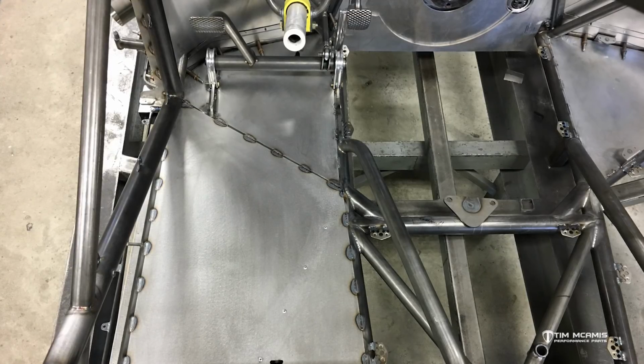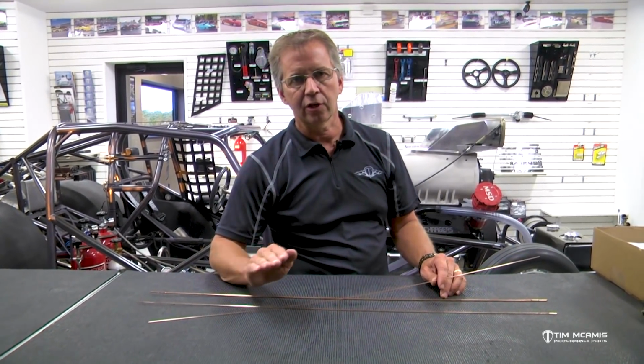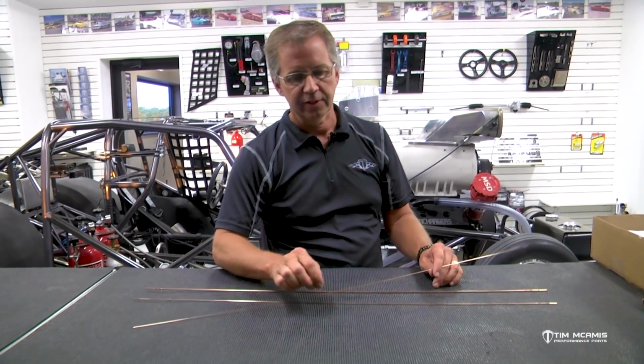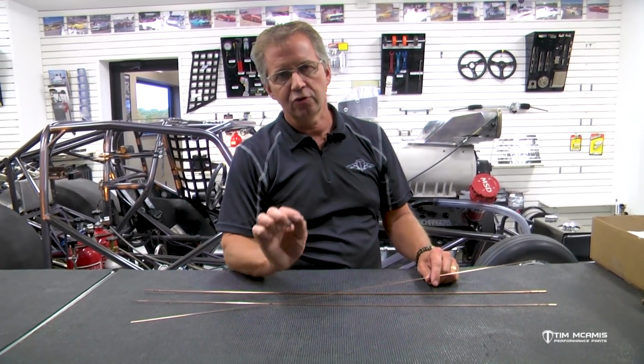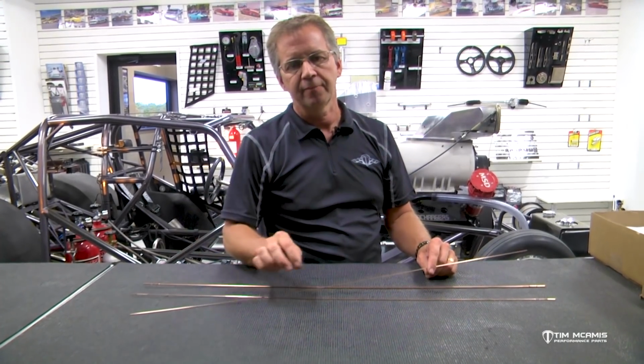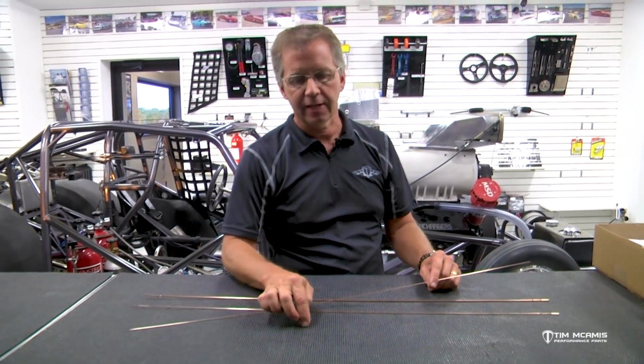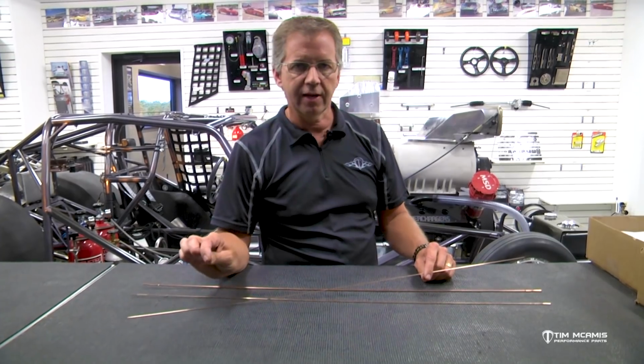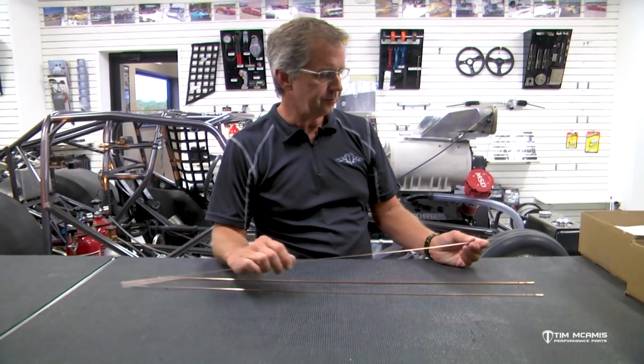And when you do that, what you want to do is we call it a little zip tack, which is just a little fusion tack on the end of each 1 inch mark, because you don't want to start welding that and then the sheet metal starts to roll up. So even though you're using a small rod, if that metal starts to pull up, then your weld's going to look all humped up and your material's not going to lay nice and flat. So you go around there and you just take the tungsten and you just zip tack it on each of the 1 inch marks, and that'll hold that down tight so that you can go back through and weld that. A lot of times we'll even put a small zip tack in the middle of that 1 inch so that we have no chance of that pulling up when we're welding it. And so this 045 ER70S2 rod is perfect for that.